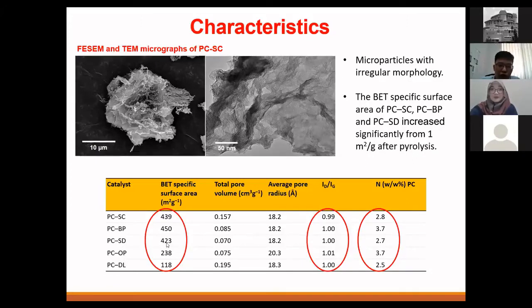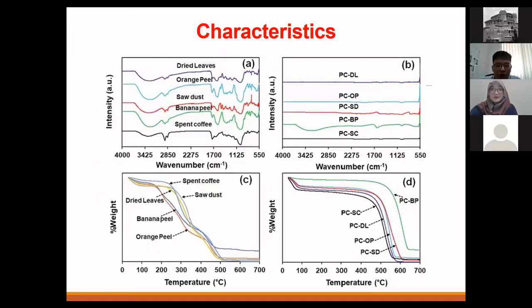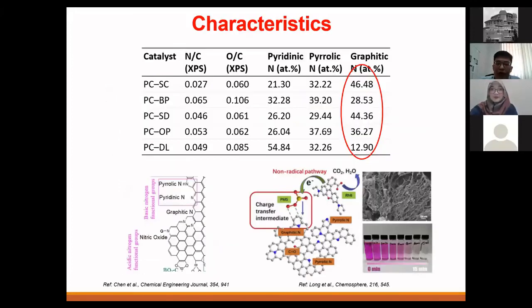Sawdust also 423. Depending on the source, if you use dried leaf, you have only 118. Okay? Just to share with you some results. What is important is that the source that you use will determine the percentage of graphitic nitrogen that you have. So this spent coffee and sawdust, if you use it as the precursor, you can see that the graphitic nitrogen is very high.